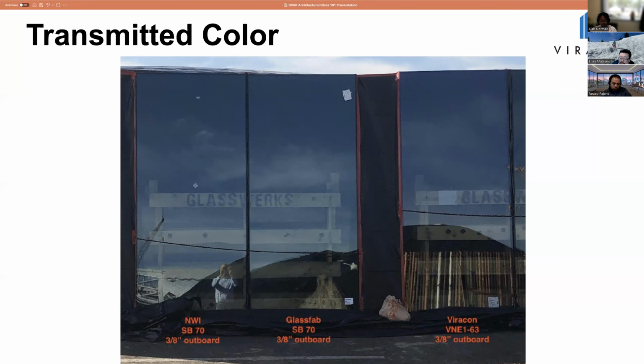When Vitro supplies samples to an architect, those samples are annealed, right? Just as Viracon's are. But when their product, SB70, gets heat treated, it actually changes the color slightly and turns it greener than the annealed sample. So if they have a building that might have heat strengthened insulated units, and then annealed insulated units, even though that's not very common these days, they would put the coating for the annealed on a clear substrate, and then for the heat treated, they put it on a low iron or Acuity, just because once they've heat treated it, it becomes a little greener.